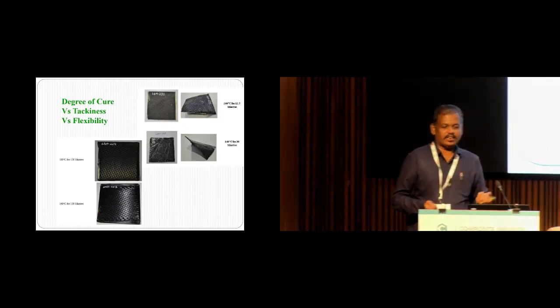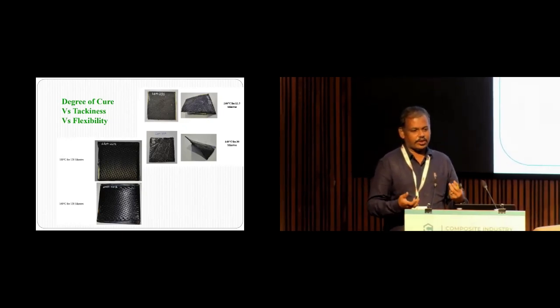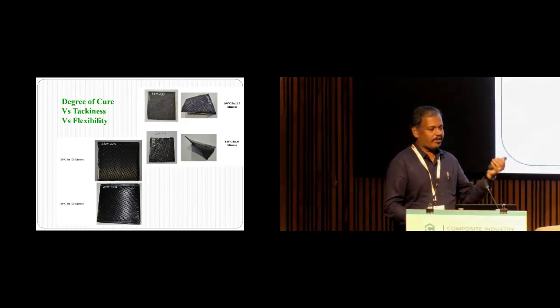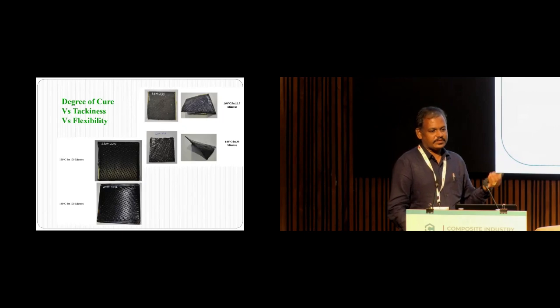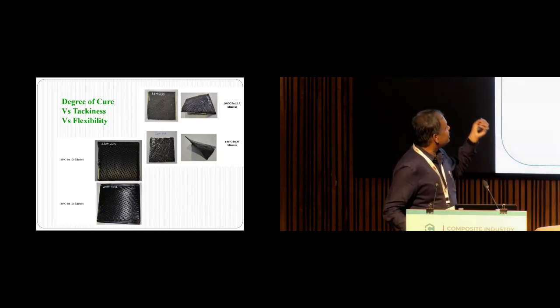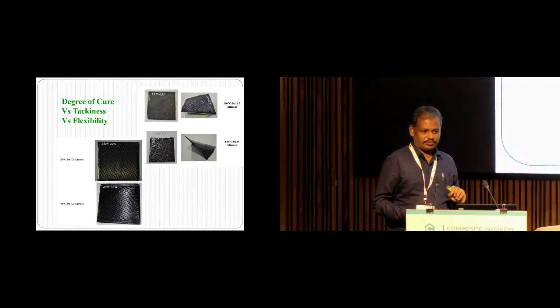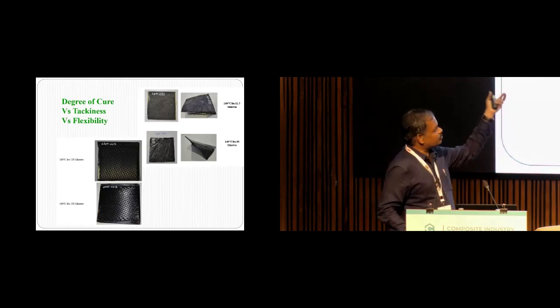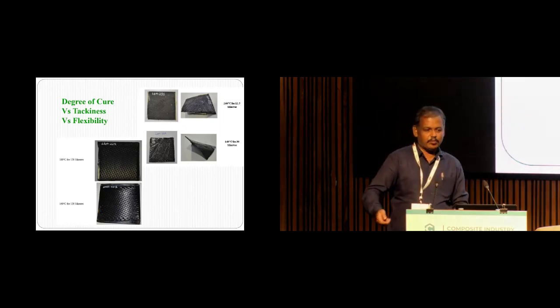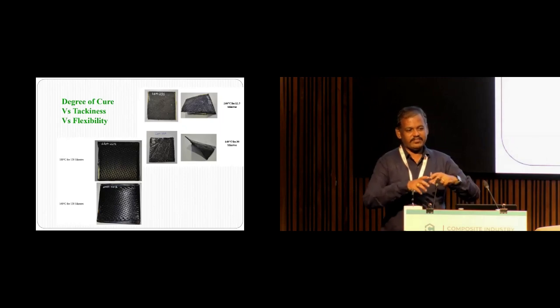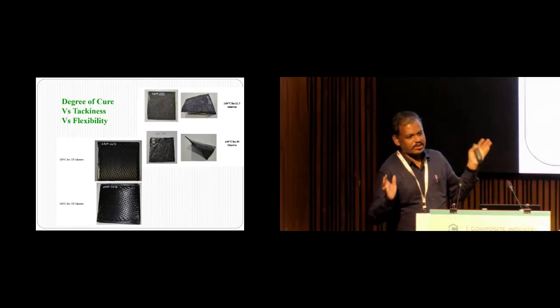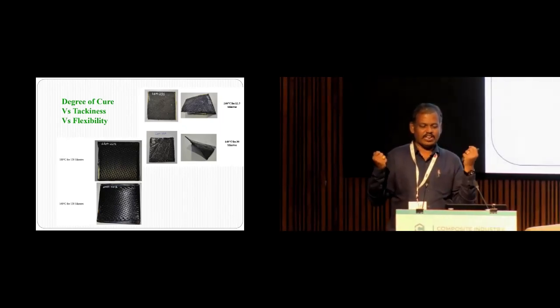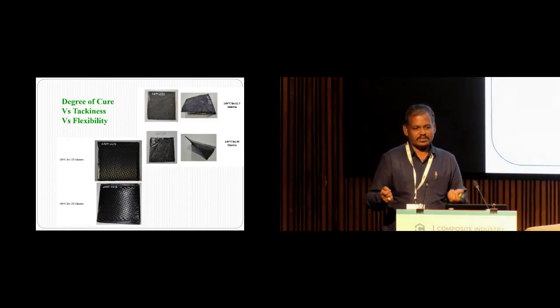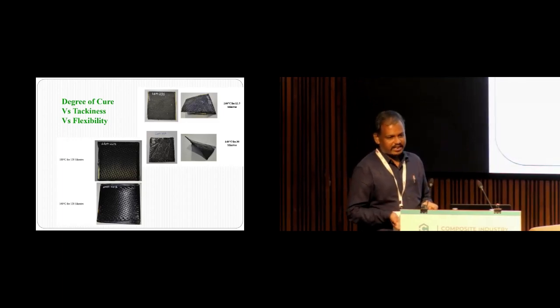When I cure to lesser curing, so when I have a curing of 30% degree of cure, what will happen? It is very tacky in nature, it is very flexible. This is a very small sample, that's fine, you can extract it. When you do it in a real RTM mold, when you extract, what will happen? Since it is flexible, the dimensionality may not be retained.